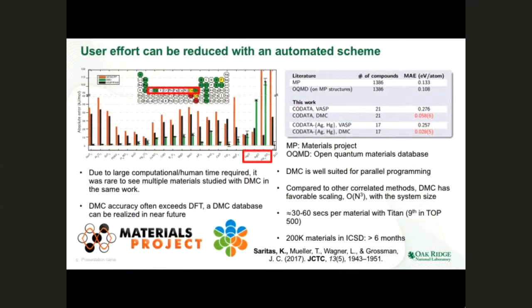And we know that the diffusion Monte Carlo, the fixed node version, is well suited for parallel programming, and it has a scaling of N to the cube, or it could be N to the power 4 as well. So this is a minor calculation that I did just to give an idea about what can be achievable using a scheme like this. So we can see that if we were to allocate the Titan for this study completely, that would mean that we will be able to get the formation enthalpy of a single material every nearly 32 seconds.